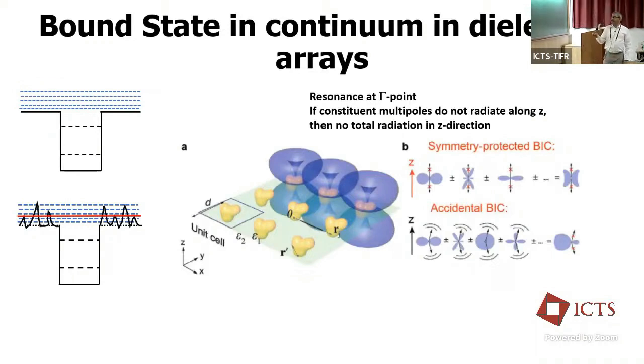But over the last 15 years or so, this has become popular in the metamaterial community because there are no metals involved. The metallic losses are not involved. So here the idea is that you can have a symmetric scattering element. If you look at the dipole and higher order multipoles, the vector sum of them will make sure that in a symmetric case for normal incidence, your dipole will be dominant and the vector sum will give you the scattering or emission in one particular direction. Similarly, we can have a random shape of this scattering element, and the vector sum of these you can design to come at one particular angle.